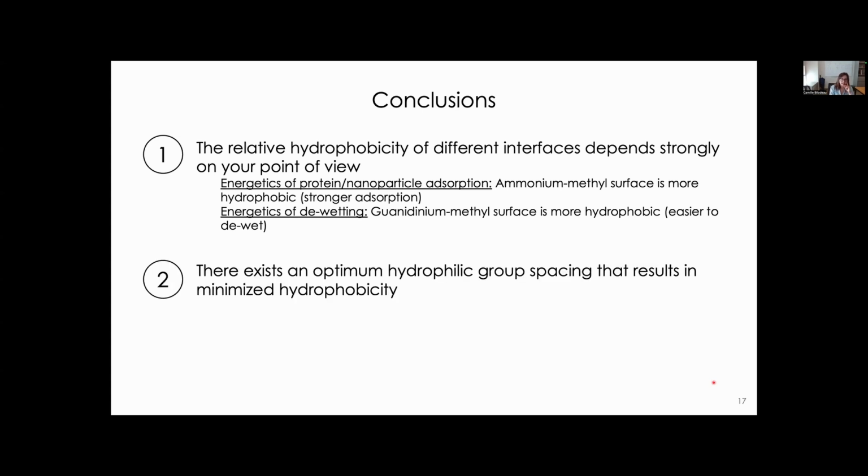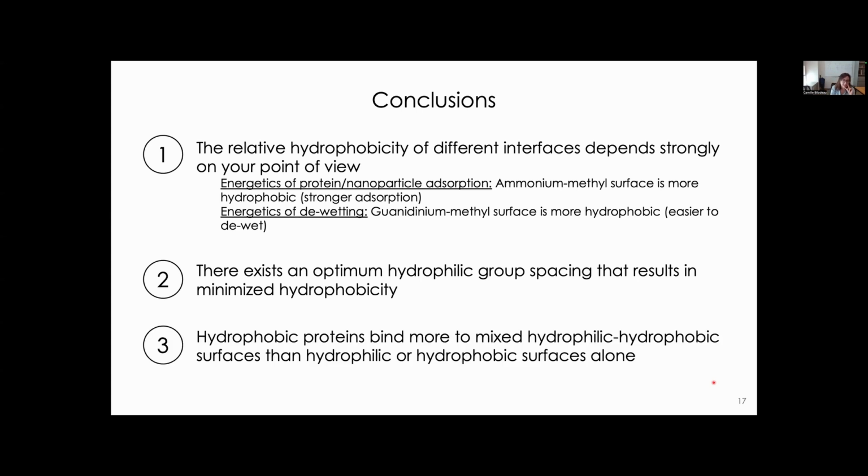We also saw that there exists an optimum hydrophilicity or hydrophilic group spacing that results in minimized hydrophobicity, somewhere around the S1 to S2 spacing. And then finally, hydrophobic proteins like hydrophobin seem to bind more strongly to mixed hydrophilic hydrophobic surfaces than hydrophilic or hydrophobic surfaces alone.